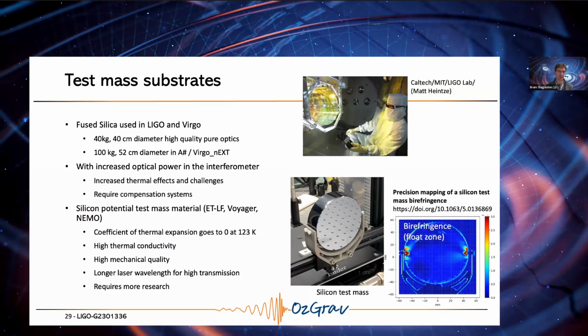at the operating point. Of course, now one idea is to use silicon as a potential test mass, although it's not in the pipeline for the A-sharps and the Virgo Next, because the key driving force is that at 123 Kelvin, the thermal expansion goes to almost zero. And that then, of course, means there are no thermal challenges, or very little. The trick there is, of course, that we need to have, as I alluded to before, longer wavelength laser sources.